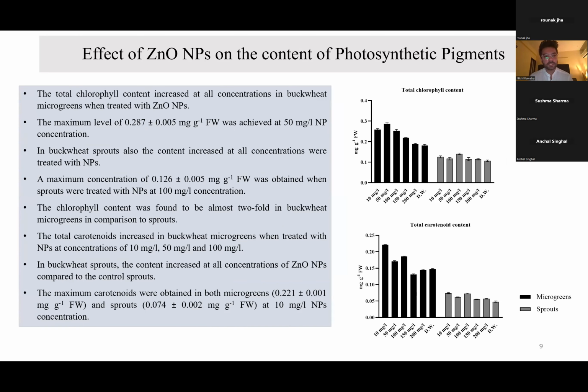After this, the effect of zinc oxide nanoparticles on the photosynthetic pigments, the total chlorophyll content increased at all concentrations in buckwheat microgreens when treated with zinc oxide nanoparticles, with a maximum level of 0.287 mg per gram that was achieved at 50 mg per liter concentration of nanoparticles. In buckwheat sprouts, also the content increased at all concentrations when treated with nanoparticles. The chlorophyll content was found to be almost twofold in buckwheat microgreens in comparison to sprouts. The total carotenoids increased in buckwheat microgreens when treated with nanoparticles at 10, 50, and 100 mg per liter concentration. The maximum carotenoids were obtained in both microgreens and sprouts at 10 mg per liter concentration. So this 10 mg per liter concentration was optimum for the increase in the content of carotenoids in both microgreens and sprouts.